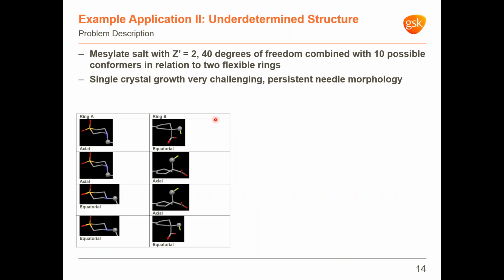Moving now to the second example I am presenting. Here is a more challenging case for which we really struggle to unambiguously identify the most convincing structural model from the XRPD structure solution step. We are now talking about the mesylate salt of a larger parent API molecule with Z'2 and 40 degrees of freedom in the asymmetric unit for 10 possible conformer combinations in relation to the presence of two flexible rings. The table shows the possible combinations on one independent molecule labeled according to the conformation of the relevant substituted position.